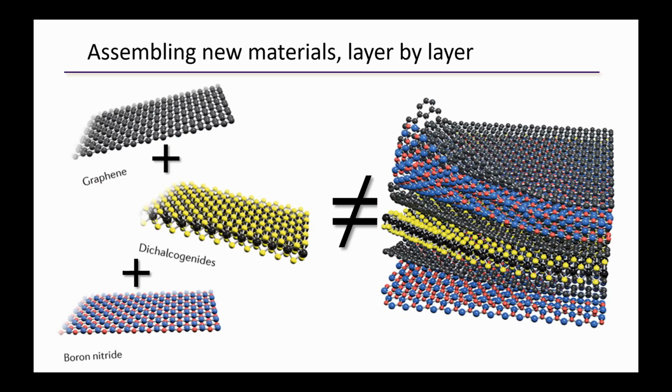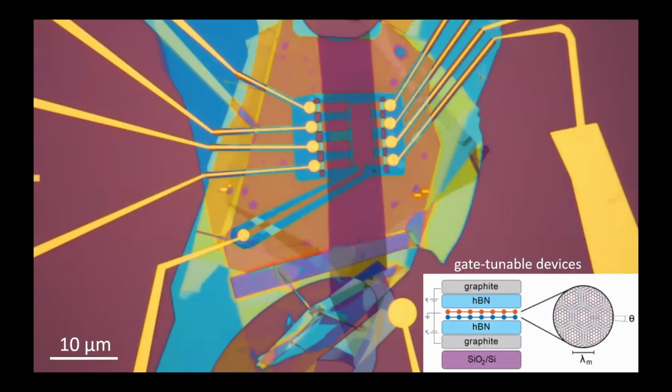And the benefit of doing this is that you often get emergent properties in these composite heterostructures, because the electrons in 2D materials live entirely on surfaces and therefore hybridize very strongly with neighboring layered crystals. So you can basically engineer new properties into materials by cleverly stacking and twisting the layers on top of each other.